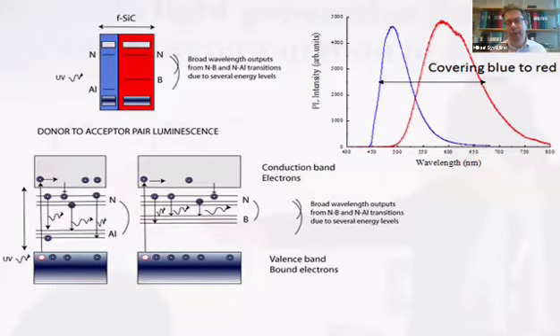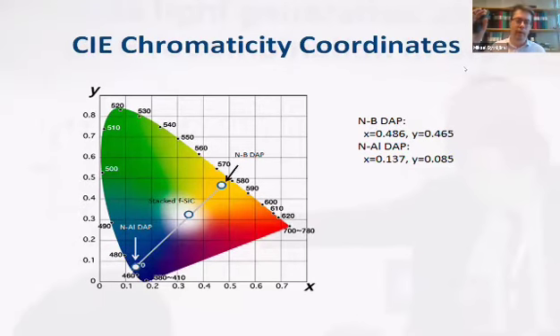And the basic principle here is that you have donors and acceptors. And when there's a recombination between these different levels, there is a broad range of energies. So it's not a sharp peak, it's a broad band, which is emitting from the silicon carbide. And then if you do this in 2 layers with 2 different acceptors at different level, you get 2 broad spectra. And if you do this in 6H silicon carbide, which has a band gap of 3.0 electron volts, then it comes out in the visible region. And all combined, this is then a pure white light. So this is the basic principle. And if you combine these 2 layers, one which is more warm white and one which is more blue, then you can get a pure white light. And this is one of the attractive features with this silicon carbide LED.